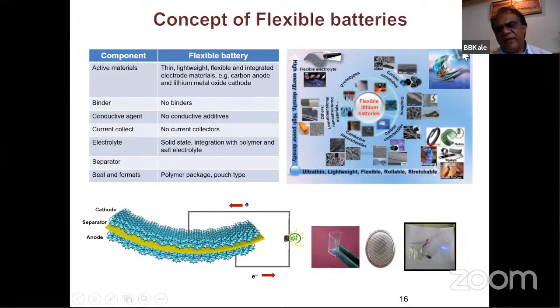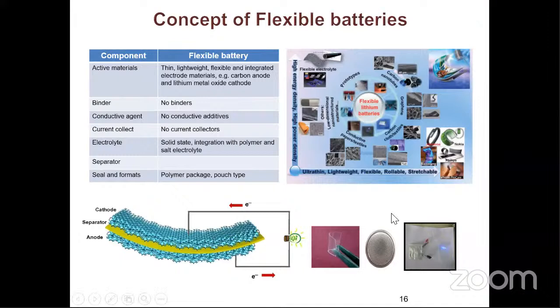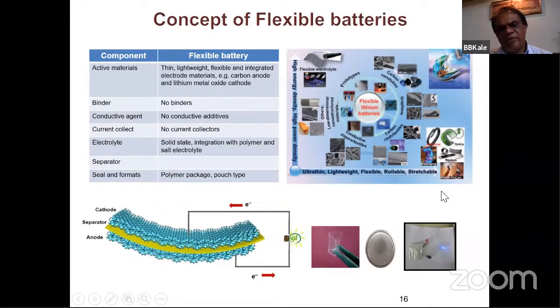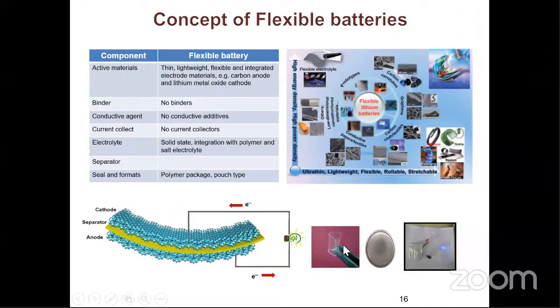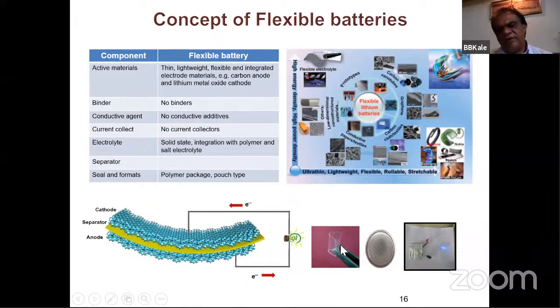Then flexible cells, we are making them. You can see that we have made a rollable cell. We can roll it and still see that the intensity is not coming down. That is made out of our polymer electrolyte. You can see our polymer electrolyte here, and we developed this polymer electrolyte. But still we have a problem with it. It can go up to more than 200 cycles, but still we are facing a problem. So we are modifying this electrolyte.